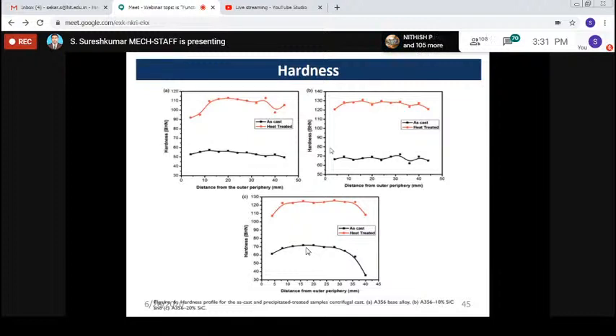At the outer edge, about 5 mm, 10 mm from the outer edges, more reinforcement is available, so it ends up with more hardness in all the conditions. When you move towards the inner periphery, the hardness value obtained is less. It slowly, gradually decreases as you move towards the inner surface of the material, so there is a gradual decrement in the hardness. Again, as I told you, wherever you need a hard surface or rich section, there you can increase the reinforcement.